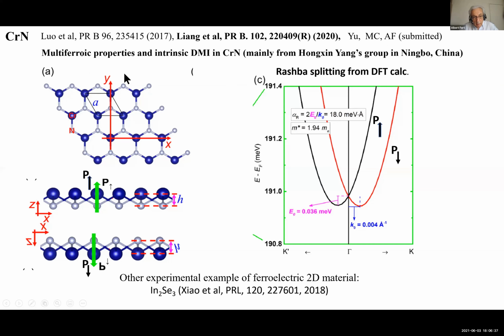This is a hexagonal structure like graphene, except that there is some buckling of the structure, that is, the nitrogen can be below the plane of the chromium or above. And of course, what can be shown in several theoretical papers is that this gives rise to a ferroelectric polarization. And so with the ferroelectric polarization up or down for these two structures, there is the possibility of going from one to the other by applying a vertical electric field, a gate voltage. And there are other examples of this type of switching between two ferroelectric polarizations of 2D magnets.